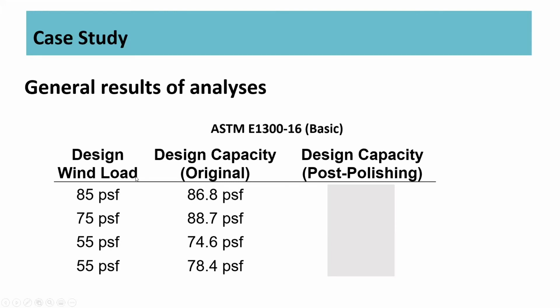And we had access to the wind loads based on the original construction drawings. And we found that indeed they were, but we did find, especially with this first one, that they were quite close. There wasn't a whole lot of residual capacity according to the basic method. And so certainly that would cause some concern: if we're reducing heat treatment or if we're reducing the thickness, so on and so forth, is that still going to check? And so it would have been nice to just continue to reuse the basic method to calculate this. But the basic method doesn't allow that because we have all these pre-calculated charts in there.